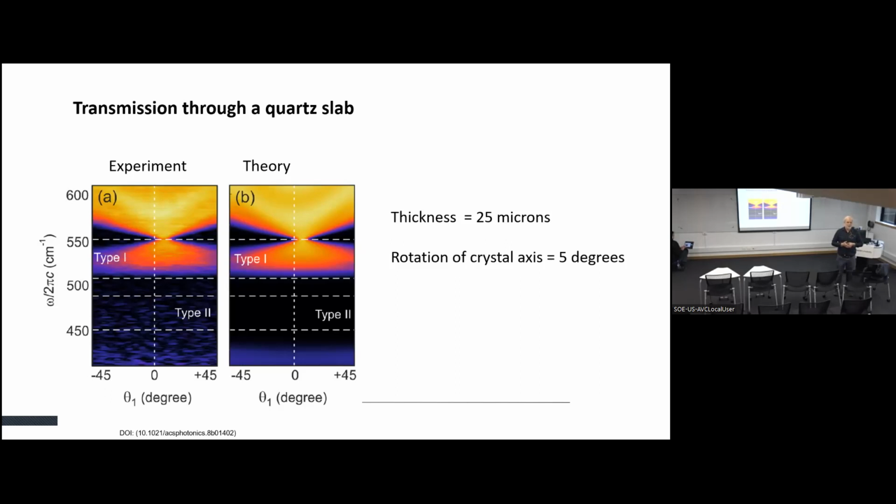It's a good question. You would certainly get some asymmetric transmission as well in the antiferromagnet because the absorption is different. The cool thing about the quartz was you don't need the magnetic field at all. The bad thing about quartz is you don't have any tunability, right? You're dependent on where the resonances sit. I kind of like your suggestion, though. Maybe I could combine the antiferromagnet and the quartz and make something really interesting. Okay.